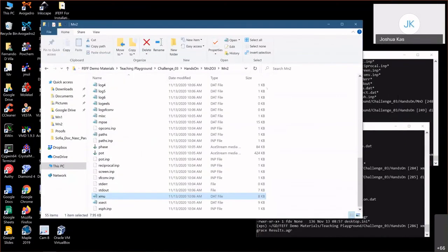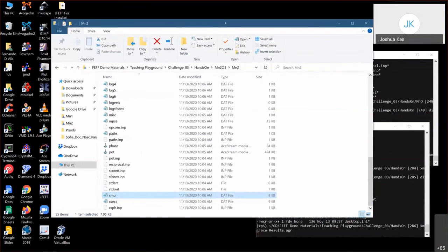One other thing on the averaging over sites, of course, you do want to be careful that you're averaging and weighting by the correct stoichiometry of the system. Precisely, and I mentioned that when I was going over the platinum nanoparticle case. You always have to average with the proper stoichiometry, and either you use the stoichiometry of your crystal, or in the case of the nanoparticle, you count your atoms in there, and you use the proper number of atoms just to get the multiplicity.